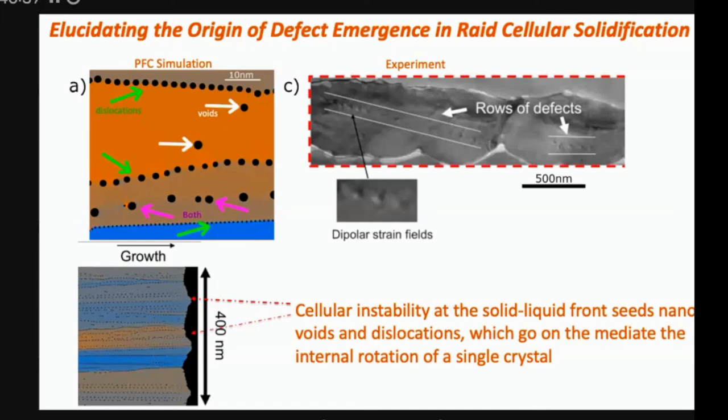So here would be a zoom up of somewhere in the back here showing either lines of defects or lines of defects and voids because they're transferable from one to another because they're so small. These voids actually are topological in nature. They carry a stress field. They can actually morph into a dislocation or collections of dislocations can become a void.